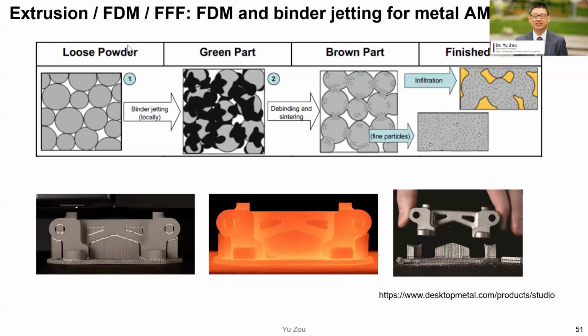So for example, this is a binder jetting process. This is very similar to the conventional powder metallurgy method. So there's a loose powder and adding binder, and then form a green part, and then you remove the binder during the sintering process, and the sintering can make the part even denser. Here I show you a sample made by this binder jetting method. So you can see the surface quality is also very good.